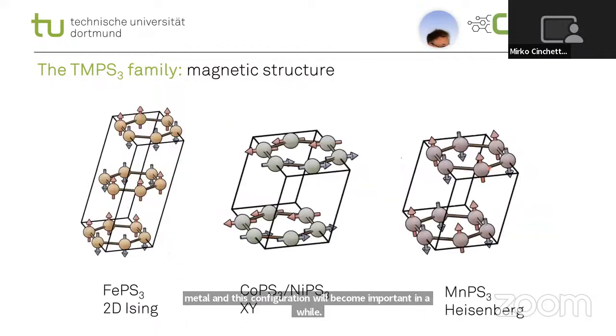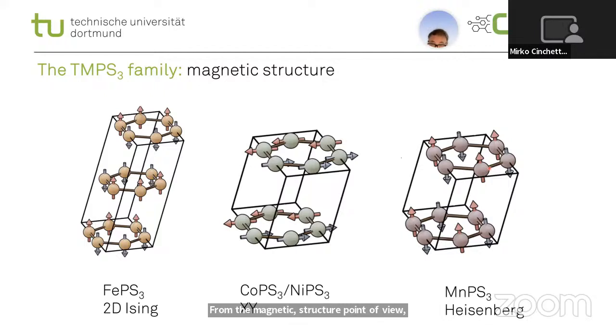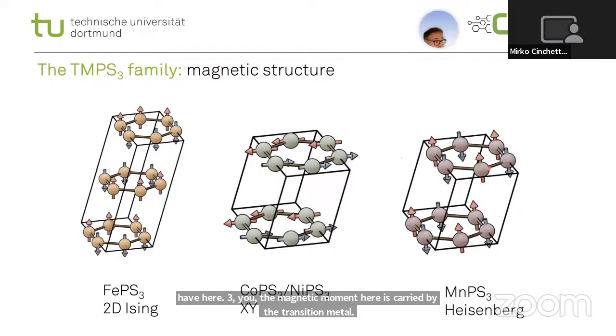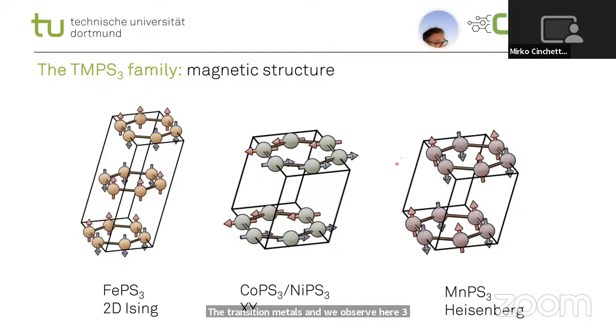From the magnetic structure point of view, the magnetic moment here is carried by the transition metals, and we observe here three types of antiferromagnetic order. We have zigzag antiferromagnetism in nickel, cobalt, and iron PS3, and Néel antiferromagnetism in manganese PS3. Nickel, cobalt, and manganese have a ferromagnetic interlayer coupling, as you can see here, while iron PS3 has an antiferromagnetic interlayer coupling. Regarding the magnetic anisotropy, iron PS3 has an out-of-plane anisotropy, while nickel and cobalt have a weak easy-plane anisotropy, and manganese PS3 has a competition between easy-axis and easy-plane anisotropy. So you see we have here a very rich magnetic behavior, although we are still dealing with antiferromagnetic 2D materials.